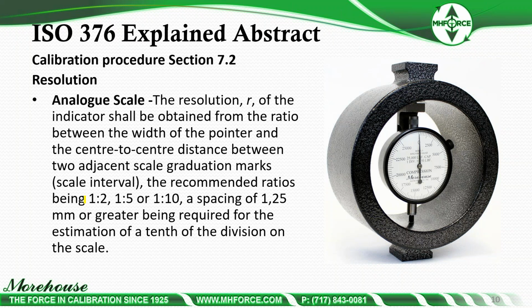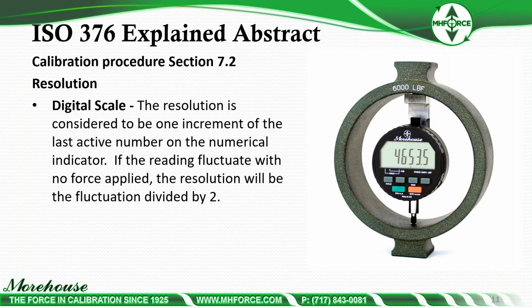The recommended ratios being 1/2, 1/5, 1/10. It then defines a spacing of 1.25 millimeters or greater required for the estimation of 1/10 of a division on the scale. So a little bit different than what most people are accustomed to. You can go to 1/2, 1/5, or 1/10. A lot of people would look at this gauge and say, hey, you can only read this to 1/2. The way I'm interpreting this is you can read it beyond that for that standard, and ASTM is the same way in that regard.